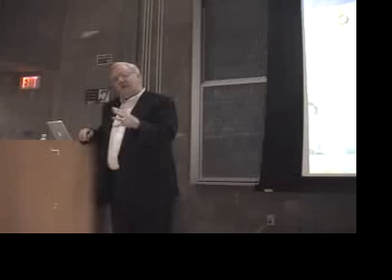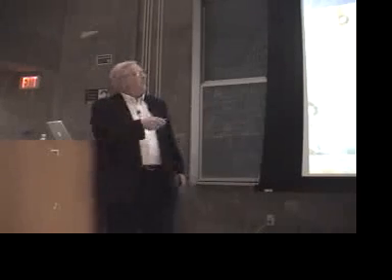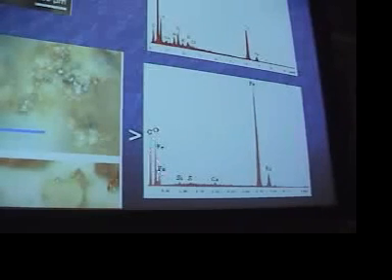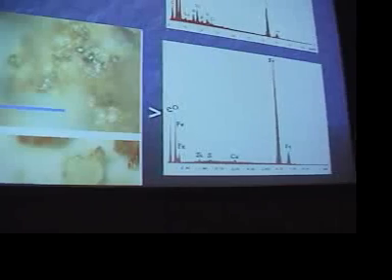So we got it to go off. I'll show you some more data on how this stuff ignites. But the point is, we see spheres rich in iron. Look at oxygen down now. Iron's much more than the oxygen. If you quantify this, it's not an exact feature, but look at the quantification. We have more iron than oxygen after the reaction. Before, we had iron oxide, lots of oxygen. Now the iron has been reduced, we say in chemistry. The oxygen has been taken up by something, presumably the aluminum.